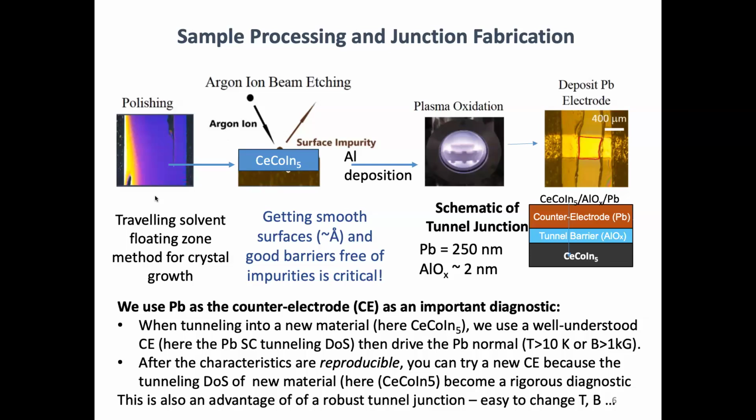It creates oxygen species, and they have no trouble going right in. We learned this in the high TC work, that you could get oxygen into a bulk cuprate easily through this plasma oxidation. High pressure oxidation squeezes things down, so it's hard to get the oxygen in. So this is nice because you have all these nice species. It makes it really clean.